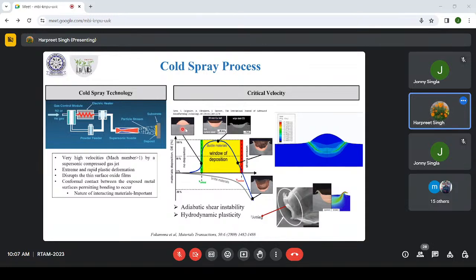You can see this is a particle and this is the substrate here. Some kind of bond will start forming. Then as we keep on increasing the velocity, there will be a good bond here, as you can see, and a very high deposition rate. Although deposition happens at lower velocities, at a certain range you will get very good deposition in this form. In fact, this is the ideal thing, I'll come to that. And you will get very nice deformation of the particle as well as the substrate, giving very nice adhesion between these two.